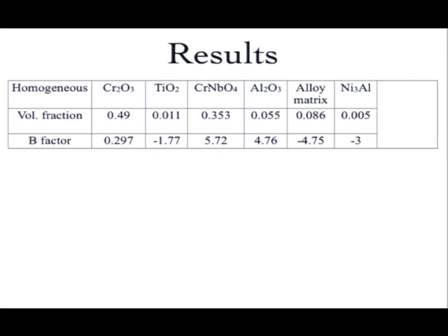Because, for example, you get the nickel-based alloy that is 8.6%, but is in reality your big sample, okay? And in fact, this kind of sample is better to treat in thickness of the layer. Then you are more interested in the thickness of the layer than volume fractions that are meaningful. And you look at the B factor, okay? So you see, in fact, the matrix B factor goes down, becomes negative quite a lot, and the top layer, what probably goes on top, gets a very high B factor.